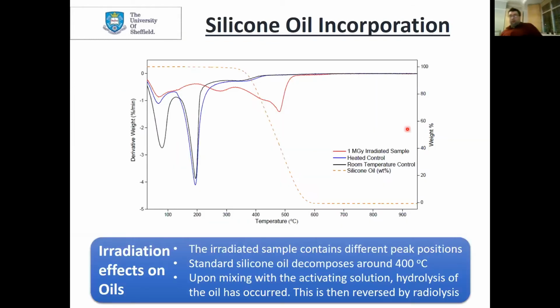I talked at the start about silicon oil, and impregnating silicon oil within these samples has actually done some interesting things. If you compare this black and blue line - the room temperature and heated control samples respectively - we see this standard water peak, and another drop at 200.